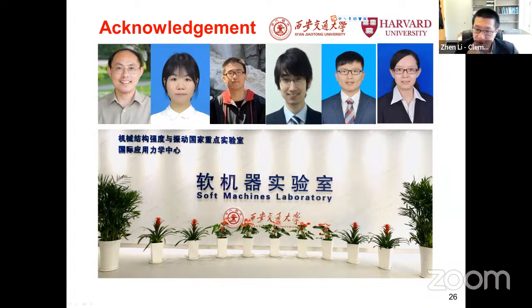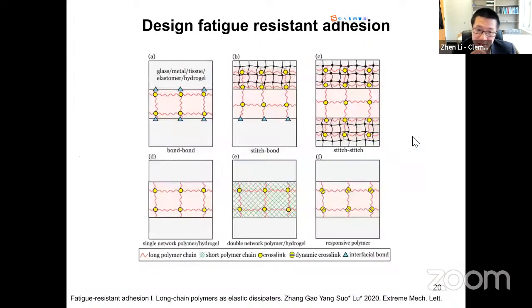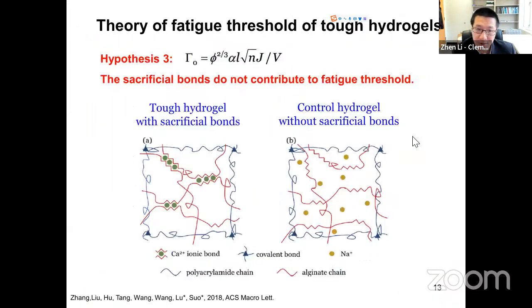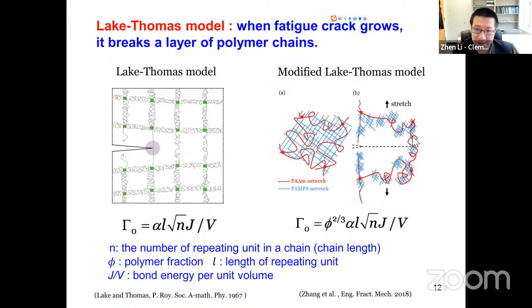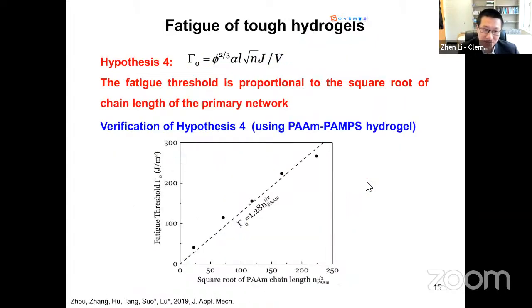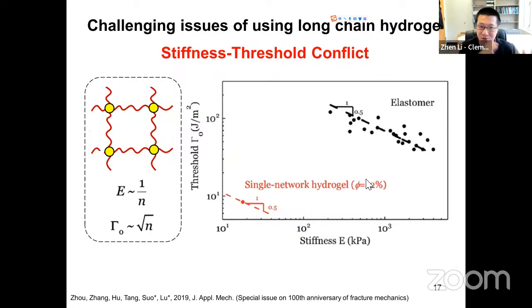Dr. Lu, I have a question about the toughness as a function of the chain length of the primary network. Based on the observation you mentioned, the toughness is increasing with the chain length. So if you use a very long chain length, you can get a very good double network performance. Is there a plateau you can reach? I guess it's impossible to continue increasing the length and reach better and better performance. Is there a kind of plateau, or an optimal chain length region you can reach for that high performance hydrogel?